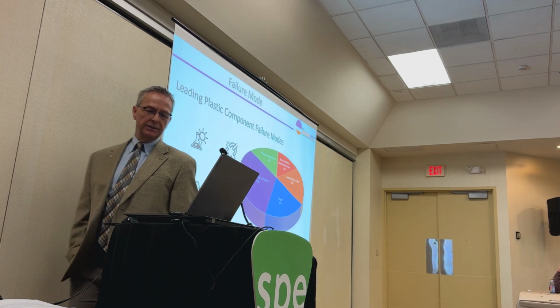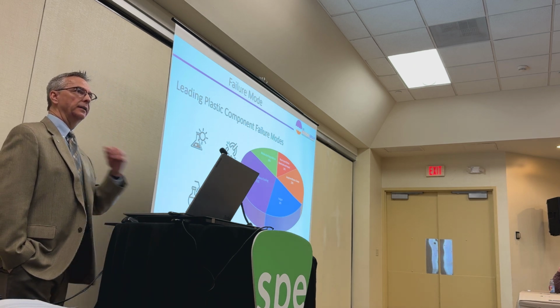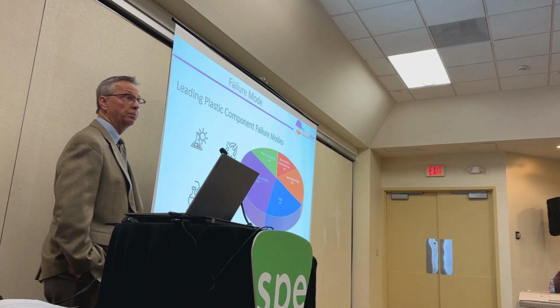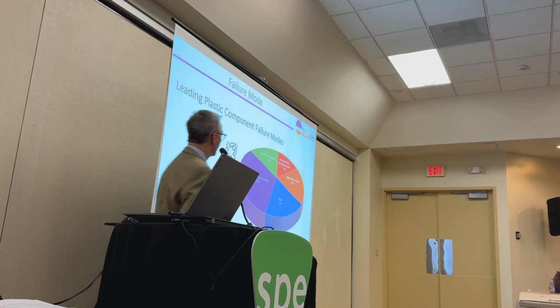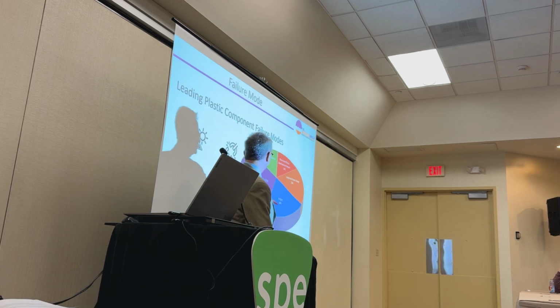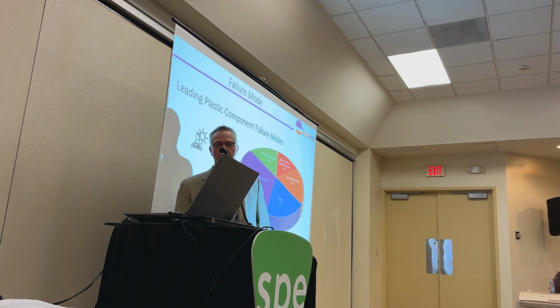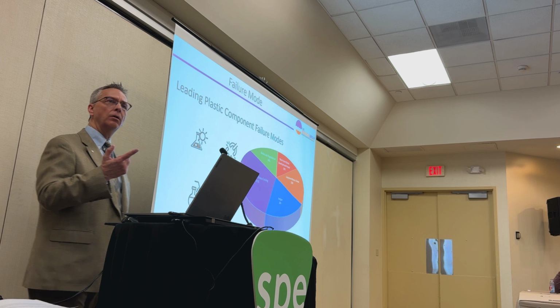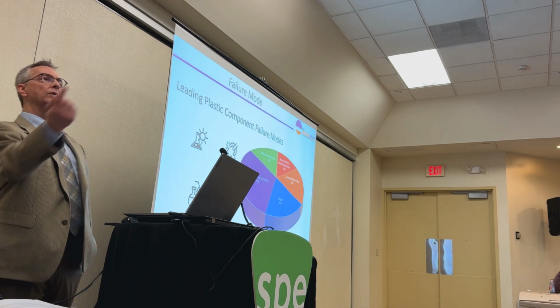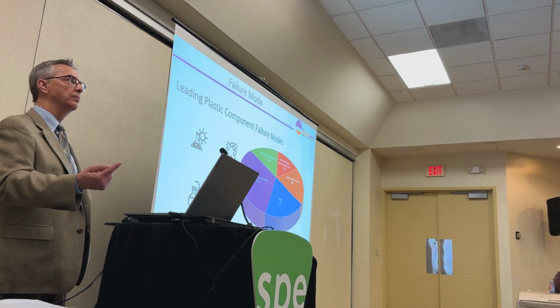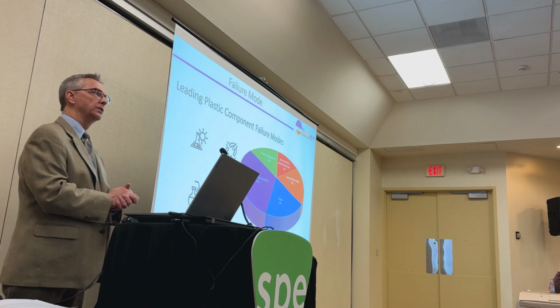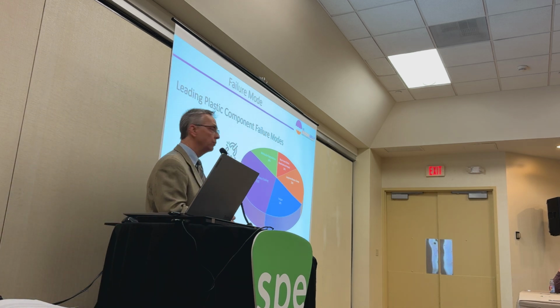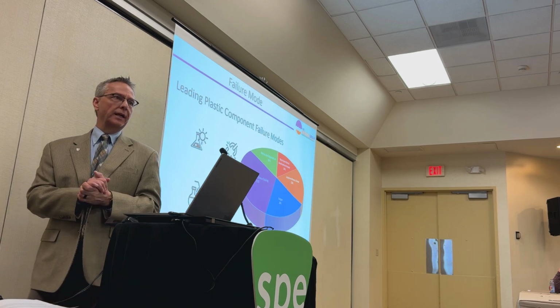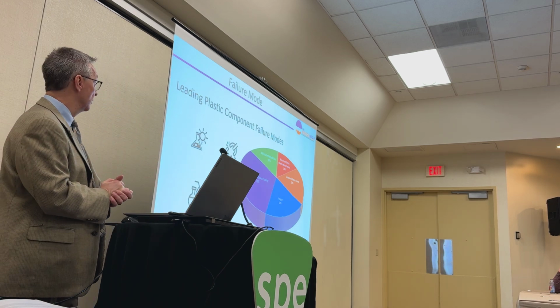In my experience, and I've conducted a lot of failure investigations, thousands of them, I would say that this is right on the money. Nearly 1/3 of the parts that fail that are plastic fail through environmental stress cracking. Creep's not far behind that. I typically don't see quite as much fatigue, but again, molecular degradation, short-term overload. All my clients automatically default to overload. Well, somebody overloaded this part. Somebody did something to it, they applied too much stress. Actually, overload is very, very rare. Overload itself, if we separate those two, is probably under 5%. Rarely is overload an issue, okay?